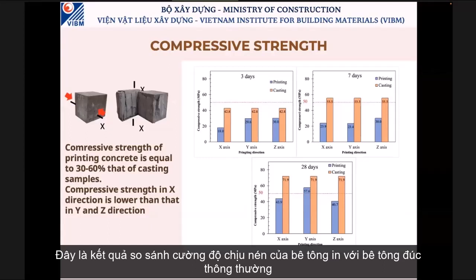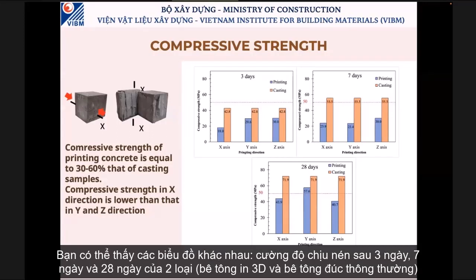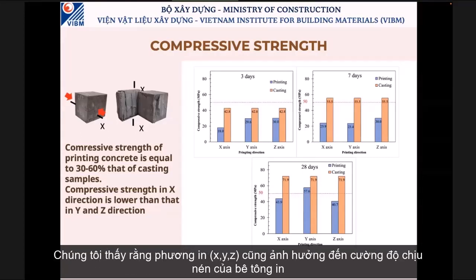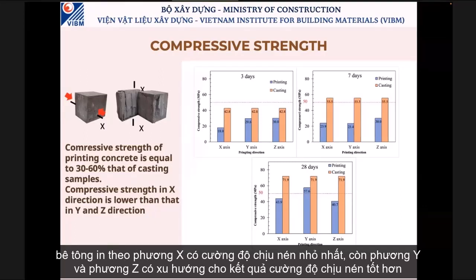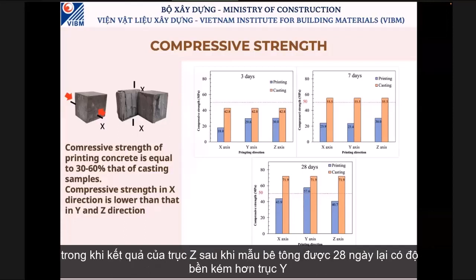Right, with compressive strength, we also compare with cast specimens. You can see here in the different graphs 3-day, 7-day, and 28-day compressive strength. And the printing direction really influences the compressive strength. We found that the compressive strength of the x-axis specimen is the lowest one, and the y-axis seems to have better compressive strength, and the z-axis is also higher than the x-axis specimen, but at 28 days finally it's lower than the y-axis.